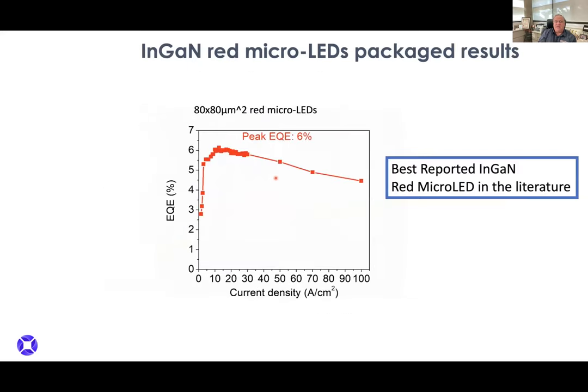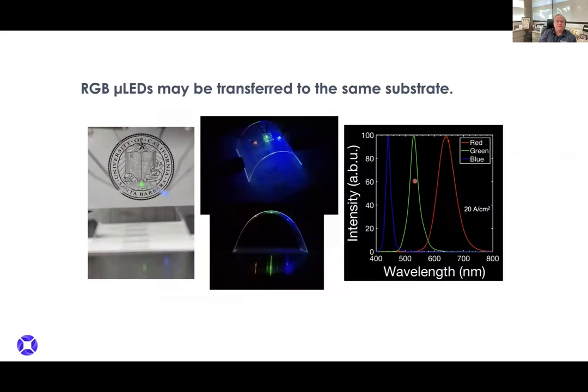And like I said, it's now 6% efficient. And it's 6% efficient right around that 5 to 10 amp per square centimeter range. So this is the best reported red micro LED now in the literature for even the last year and a half running. So now you have all three colors in micro LEDs. You have the red, the green, and the blue.